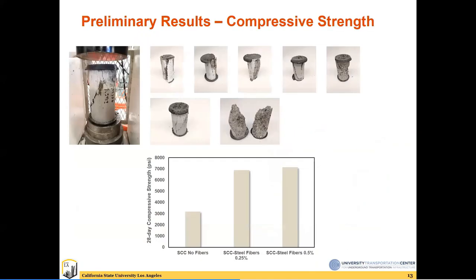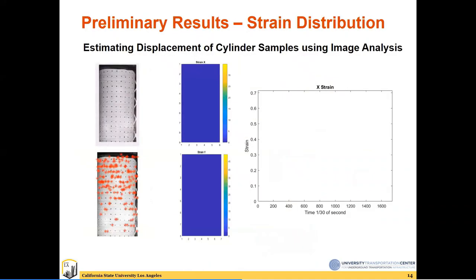Some other preliminary results of the 28-day compressive strengths, and we can see that adding the steel fiber is clearly increasing and enhancing the compressive strengths of the cylindrical samples in the lab.